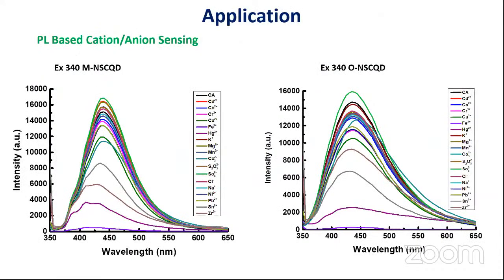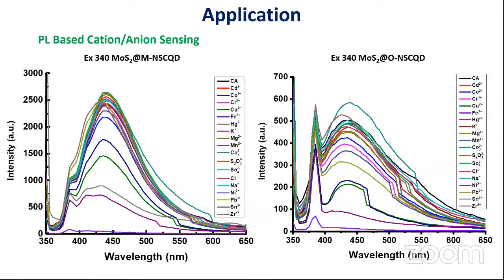And here is our application, which is PL based. So here you can see this methylene blue derived NS CQD shows better detection for iron. Here you can see iron and mercury and so on. Similarly, in this case also, onion derived carbon dot, we are getting good results for iron and mercury. Now we have loaded the carbon dot on the MoS2. So this is also showing good results for iron, mercury, and tin also.